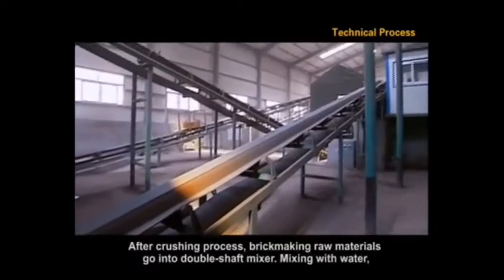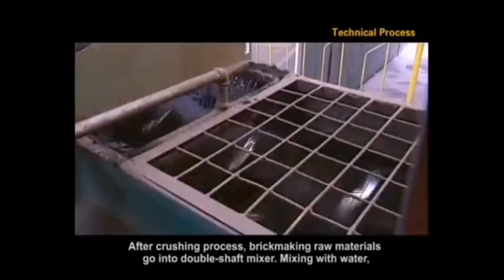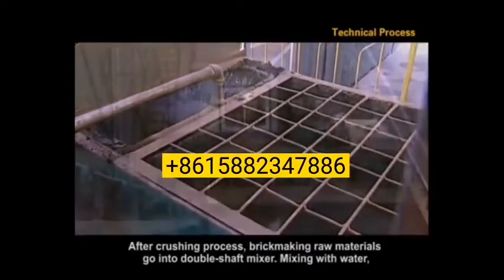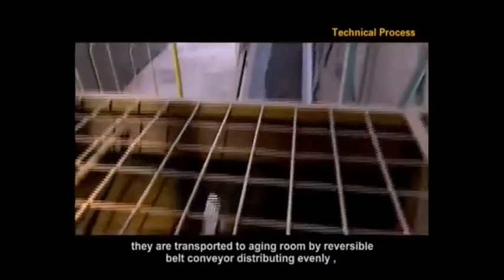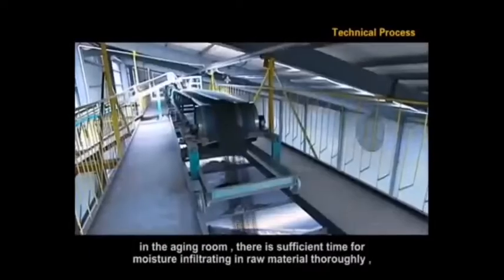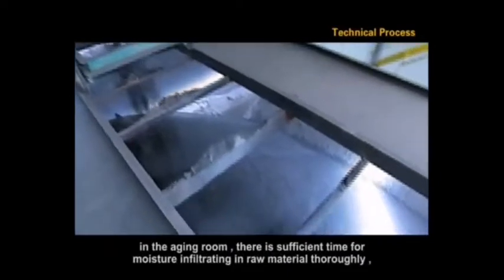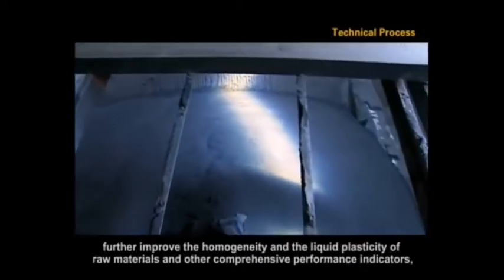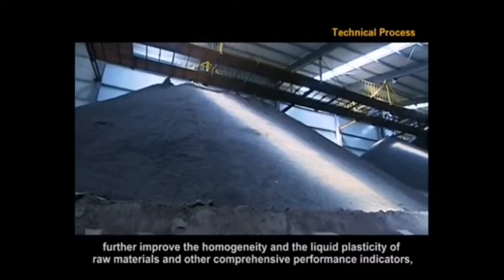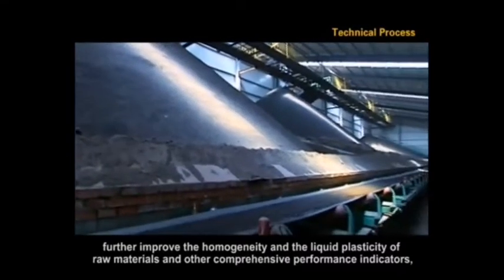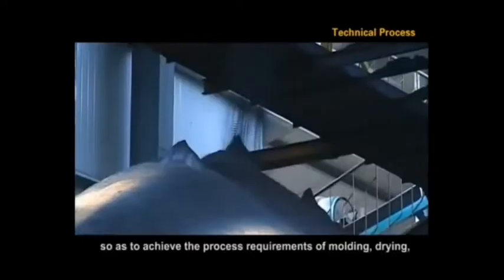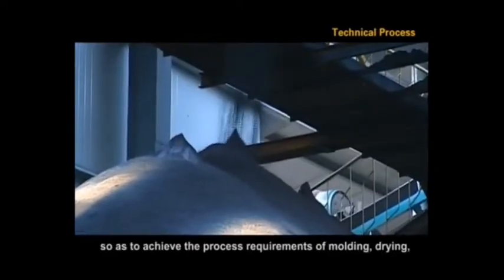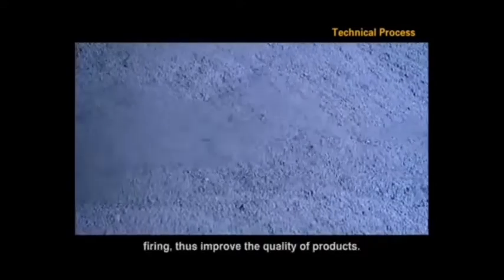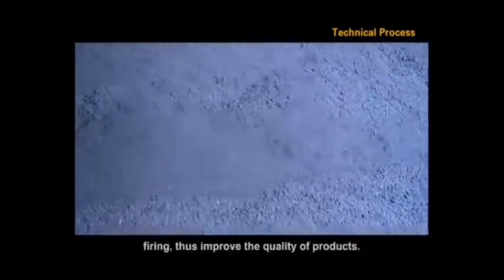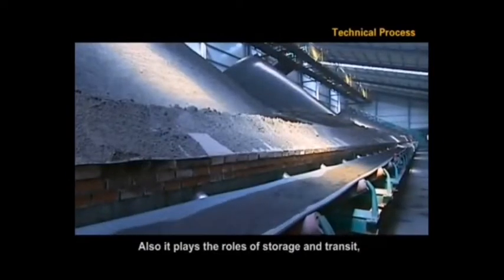After the crushing process, brick-making raw materials go into the double shaft mixer. Mixed with water, they are transported to the aging room by a reversible belt conveyor, distributing evenly. In the aging room, there is sufficient time for moisture to infiltrate the raw material thoroughly. This further improves the homogeneity and the liquid plasticity of raw materials and other comprehensive performance indicators, so as to achieve the process requirements of molding, drying, and firing, thus improving the quality of products. Also, it plays the roles of storage and transit.